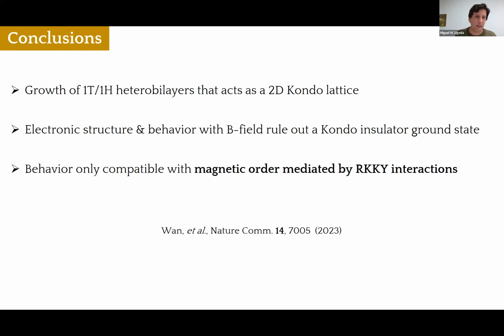We've been able to grow these heterobilayers, which act as a two-dimensional Kondo lattice. The electronic structure and behavior with the magnetic field allow us to rule out a Kondo insulator ground state. And basically, this behavior is only compatible with magnetic order, which is mediated by RKKY interactions.